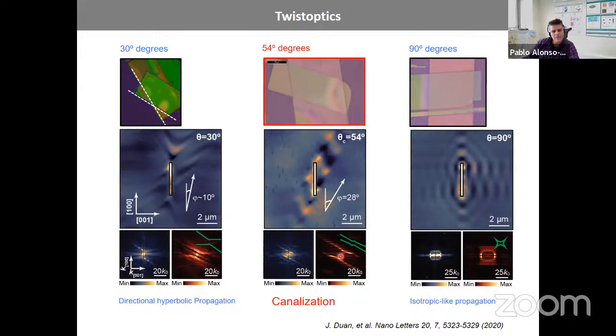Because this is k-space, okay? If you take vectors here, you have all the k's hitting this curve, which are the wave vectors that are available. But as I told you before, the pointing vector is perpendicular to the isofrequency curve. And the perpendicular to these parallel lines is just one direction. So all the energy goes in one direction. This is what we call canalization. But we have all k's propagating in that direction. So all wavelengths are available to propagate in that direction, but only along that direction.